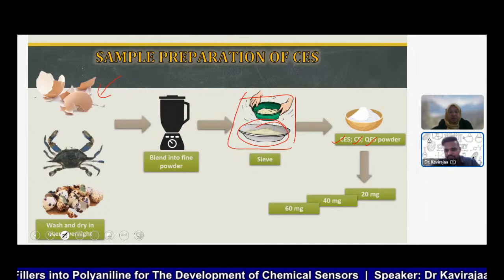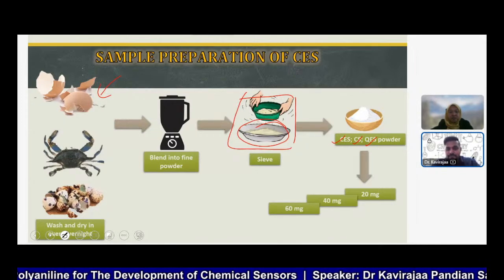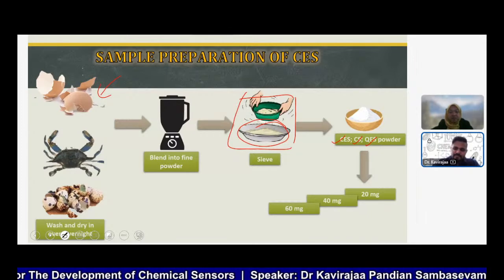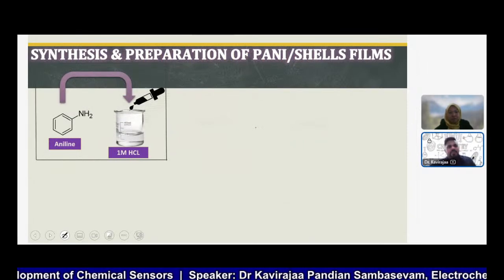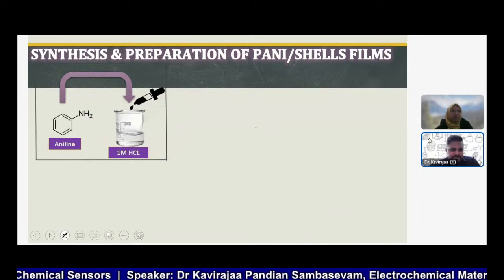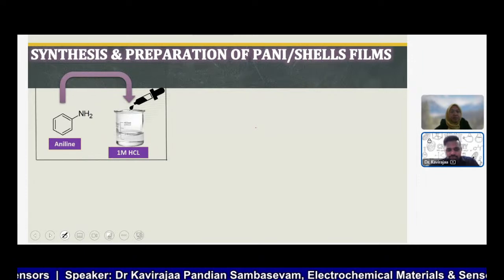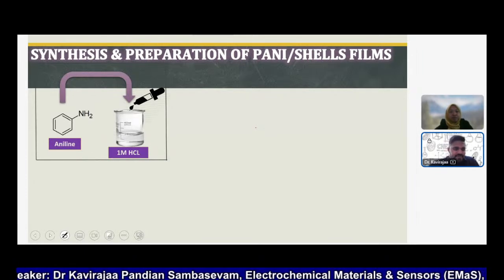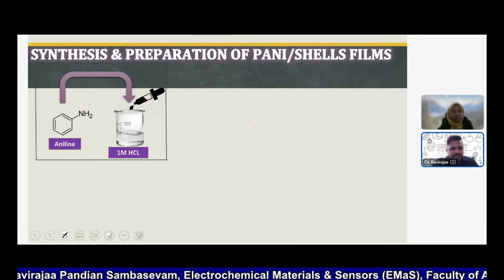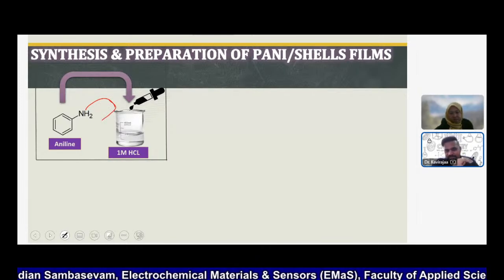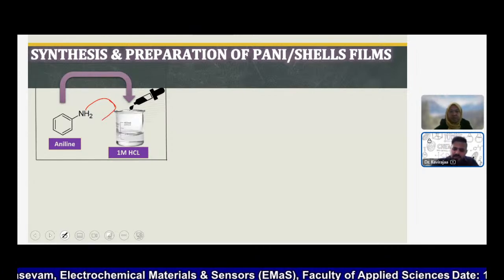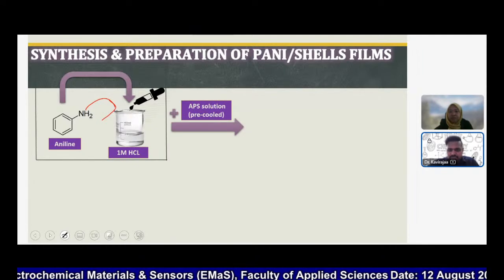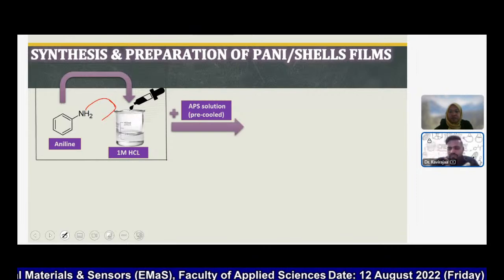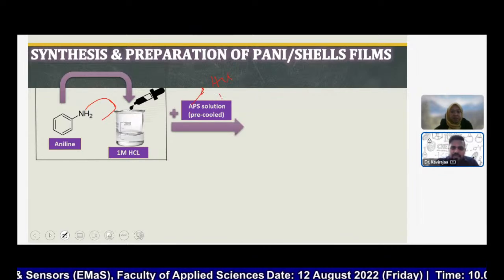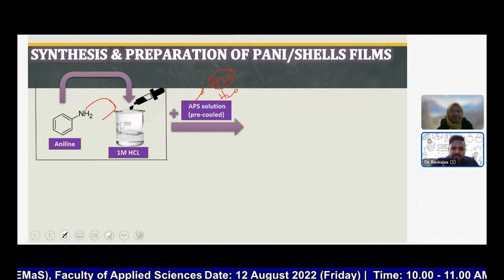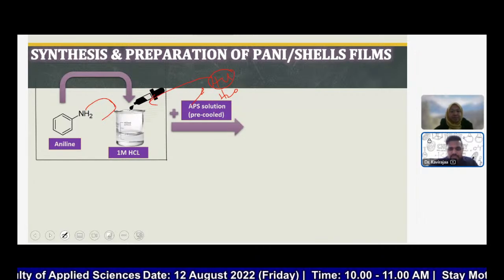We are not doing in situ because in situ the process will be a bit tedious. So we need more time to perform the washing process and so on. I will explain that in detail over here. So this is the synthesis and preparation of PANI and also shell-based film steps. The standard protocol of producing this conducting polyaniline is that we first have to disperse aniline monomer. Before we disperse, we have to make sure it's doubly distilled. And then we disperse it using one molar acid. One molar is enough. We don't need to use a highly concentrated acid. Then we add an oxidant, which is APS solution. APS is a solid, so it can be dissolved either in hydrochloric acid or maybe water. It depends. In this case, we use hydrochloric acid because we wanted to maintain the same environment. And then it will be pre-cooled as well.